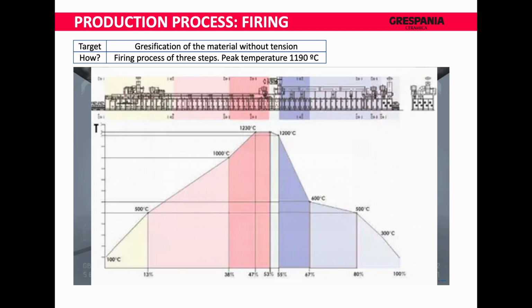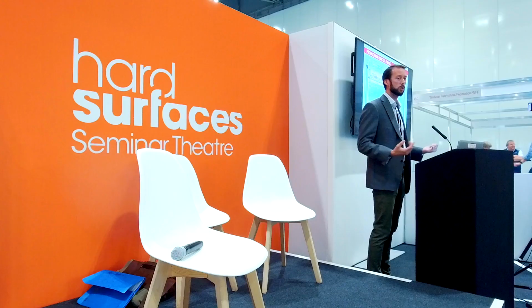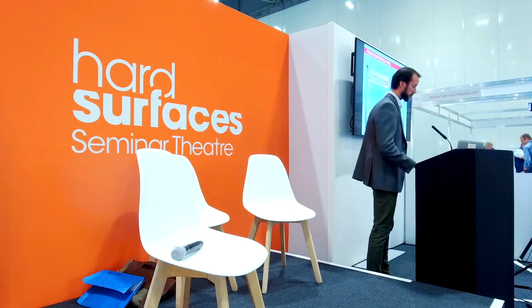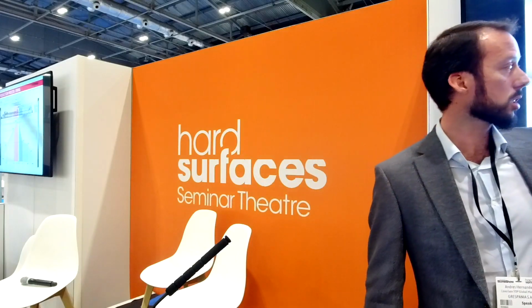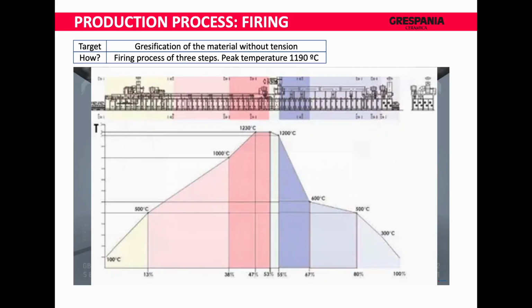That's where we can generate tension in the product, okay, because we have two layers shrinking. One is going to shrink at one rate and the other one is going to shrink at another rate. That difference in shrinkage is going to create tension in the whole product. But the benefit is that by cutting the edges, it's very easy to release that tension on this product. The last step is cooling down. Basically, after we have increased the density and after we have melted the clay, we need to solidify it again. So we use atmospheric air to cool it down.